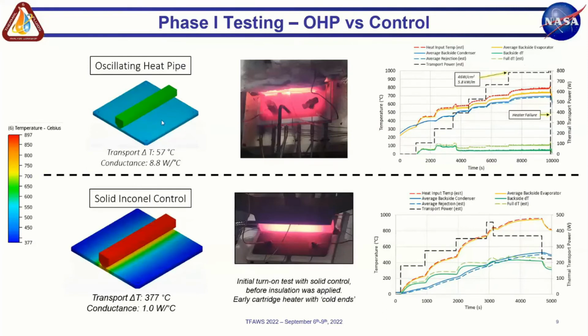So the phase one testing, on the bottom, we can see a test of this solid Inconel control. This is done before we had insulation on the heater block, but photo in the center bottom with the simulation on the left, time series on the right, essentially showcasing the poor thermal conductivity of just an Inconel plate. And then at the top, we have a mass equivalent OHP, also made out of an Inconel envelope, but with working fluid inside. And we can see the contribution of that working fluid, the ability to axially transport the heat and isothermalize the rejection surface. So nice hot part. You can see it reflected in the simulation and just visibly to the eye in the photograph of the test itself.